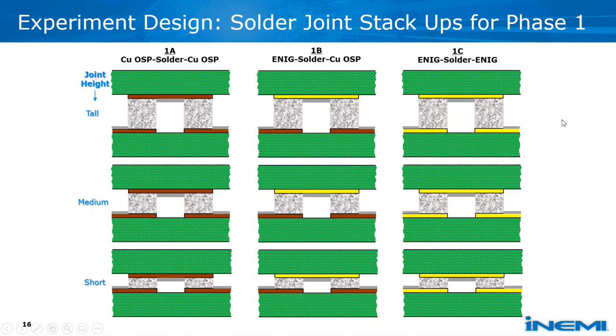This slide shows the diagrams of solder joint stack up that will be evaluated for electromigration. The 3 different heights, as I mentioned before, height is a big factor here, and you can see the 3 different heights, the bottom one being short, the center medium, and the top one tall. And then the surface finishes, as identified by the brown one is the copper OSP, and the gold, yellow gold color is the ENIG. So these 3 different combinations of these 2 surface finishes are possible depending on direction of current flow through the joints.